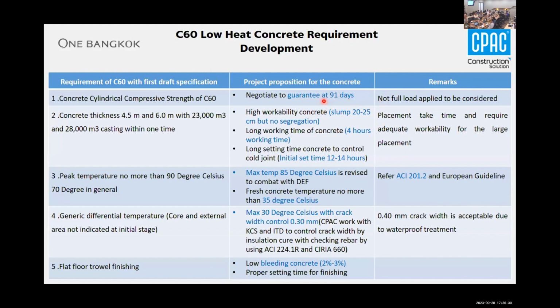So this is the number we talked about, and we would like to have high workability concrete because we cast a lot. Imagine 28,000 cubic meters: we need high workability concrete and long working time. It's around 4 hours, and the setting time is around 12 to 14 hours. The maximum temperature, as I mentioned, is 85. And the fresh concrete temperature, we control at 35 degrees Celsius. For the max temperature difference, we talked about 30 degrees Celsius in general, but in detail, we have a model from Professor Somnik and ITD to calculate the steel rebar to confirm that the crack can be controlled.